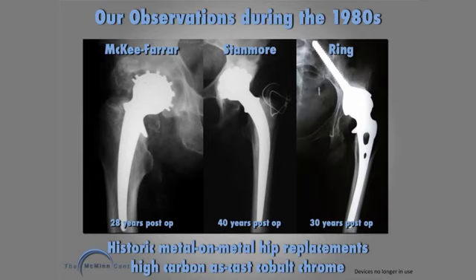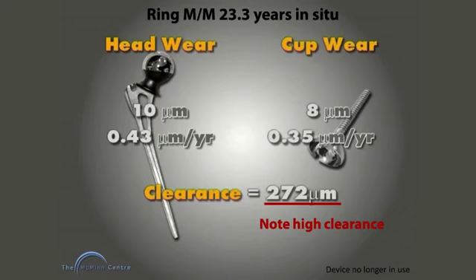When I started to think about the options for hip resurfacing in the late 1980s, it was clear to me that with the technology available at that time, metal-on-metal offered a chance of working, because hitherto no material had worked for hip resurfacing. The wear of these devices was extremely low. This is one Ring device that I removed 23 and a bit years after Peter Ring put the joint in himself. 10 microns of wear on the head and 8 microns on the cup. Exceptionally low wear in a high clearance joint.